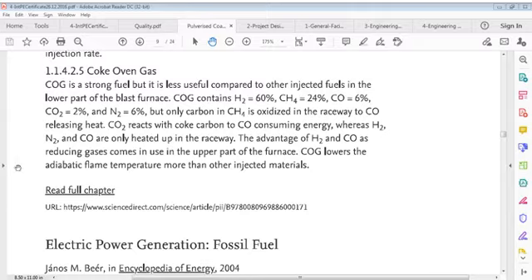Coke oven gas (COG) is a strong fuel but less useful compared to other injected fuels in the lower part of the blast furnace. Coke oven gas contains hydrogen H2 60%, CH4 24%, carbon monoxide 6%, carbon dioxide 2%, nitrogen 6%. Only CH4 is oxidized in the raceway to carbon monoxide, releasing heat. CO2 reacts with coke carbon to CO, consuming energy, whereas H2, N2 and CO are only heated up in the raceway. The advantage of H2 and CO is that they are reducing gases.